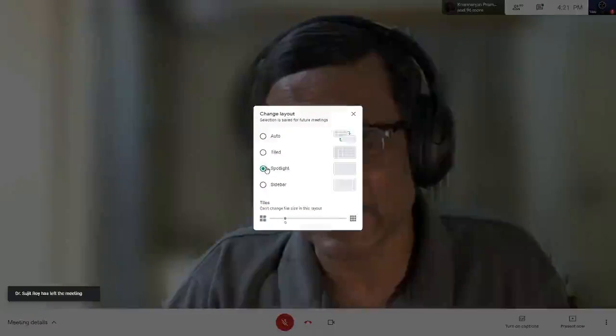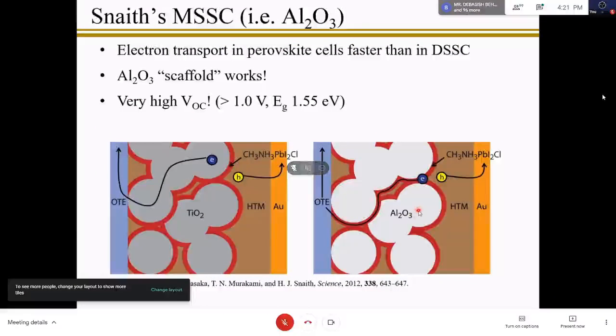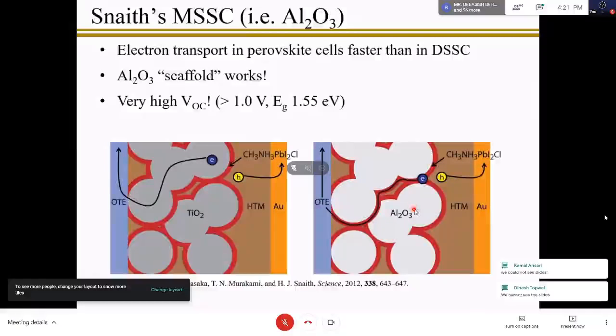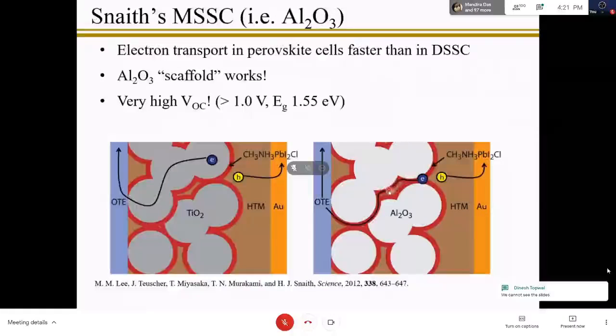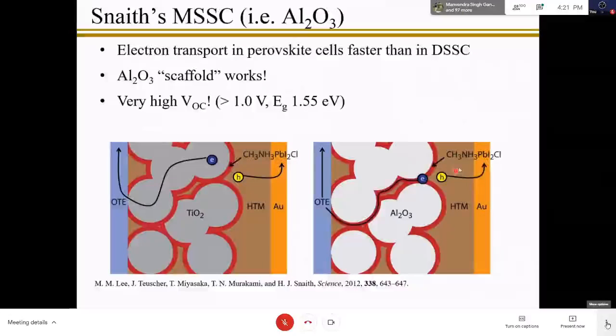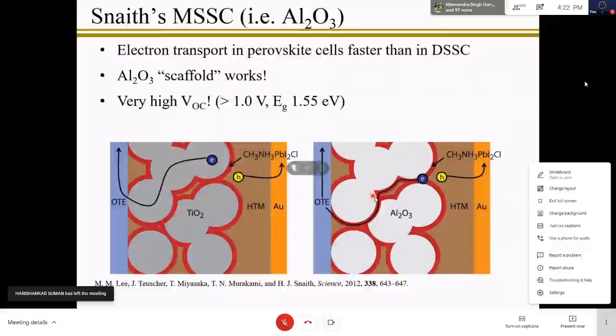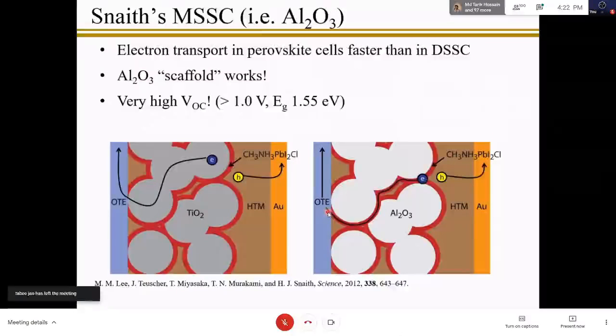But what Henry Snaith showed very soon is that you don't have to use TiO2. Instead of TiO2, you can use aluminum oxide. Now that's absolutely remarkable, because aluminum oxide has such a huge band gap. I said here the electron jumps in there because of the band alignment, which makes it easy for the electron to go there. In the case of alumina, its conduction band is so high up that the electron cannot go into alumina. So if the electron has to go anywhere, the active absorber material itself must transport the electron, and the hole was conducted out this way.